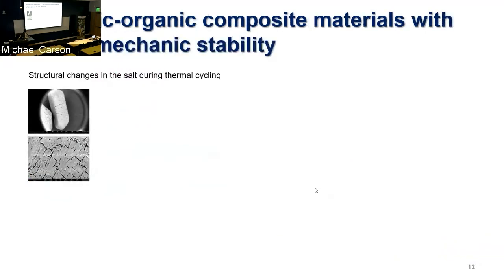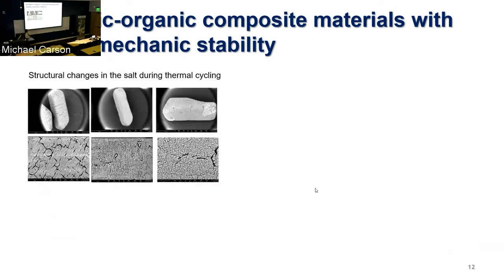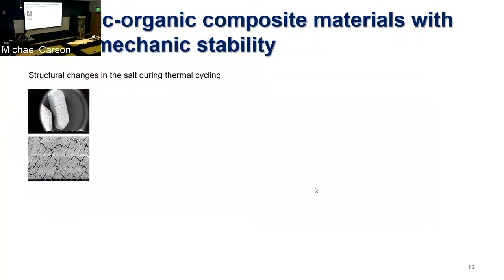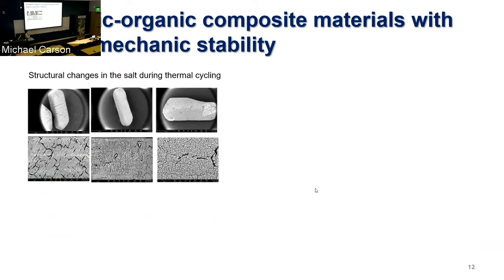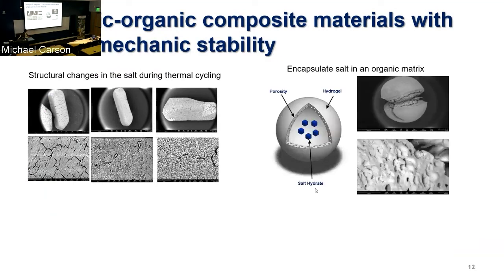So what we've been focused on is really how do we get reversible thermochemical reactions. So this is the salt after one cycle. After a couple more cycles, you can see that there's several more cracks that are formed. The microstructure starts changing significantly. So in theory, the reactions are reversible, but in practice, we see the structure change significantly.